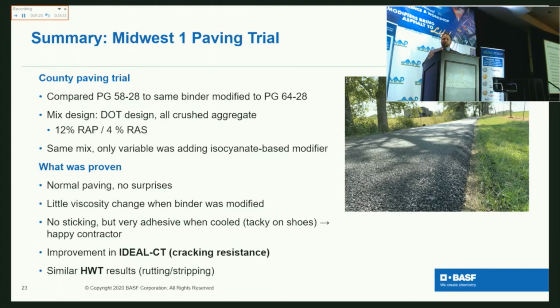At one point during the second Midwest trial, we had finished, the paver had gone by. We'd done one roll with the roller, and somebody backed out of their driveway. And of course, you see the entire paving crew freeze. They're freaking out. They're going to have to go back and fix it. And as soon as they turned the wheel, everybody ran over to look at it, and there wasn't a mark on the pavement. It was very impressive. That material had a 2.75% loading of the isocyanate-based material.